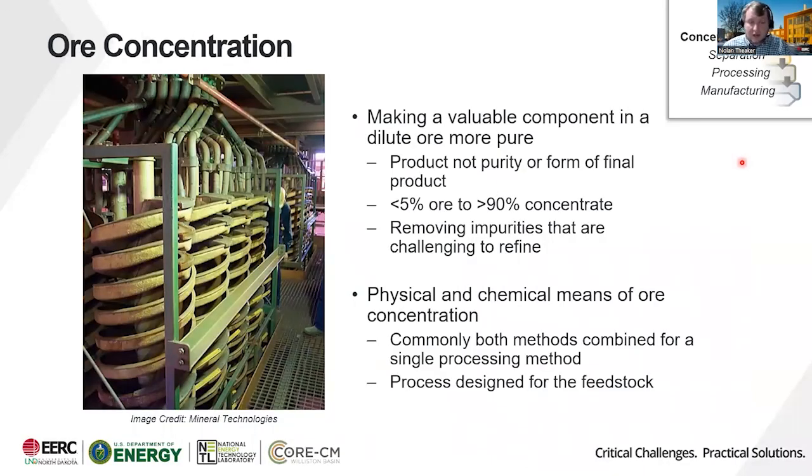For ore concentration, this is mineral processing and hydrometallurgy, and this is making these valuable components in this dilute ore more pure. Typically, it's not the right purity you want or in the final form that you want. Like, for instance, this will be less than 5% ore to about 90% concentrate, but this still isn't, you aren't going to make a product with what comes out of ore concentration.